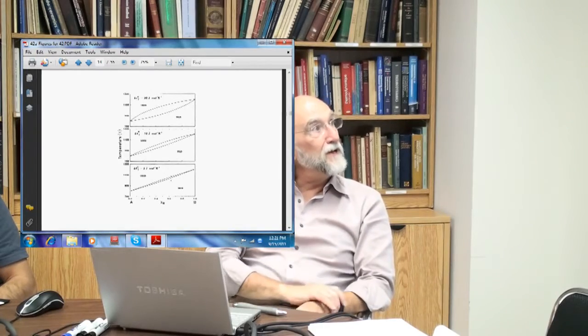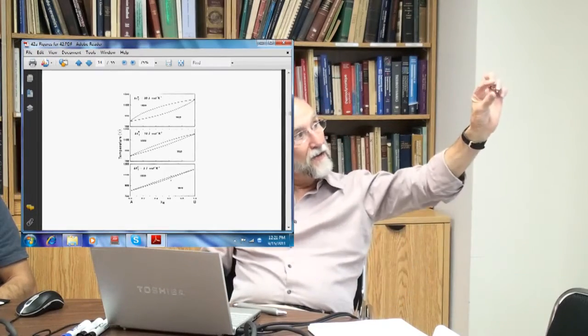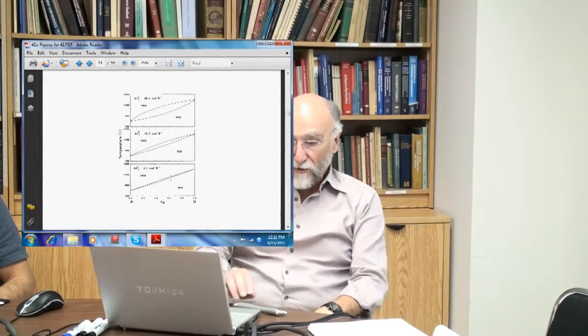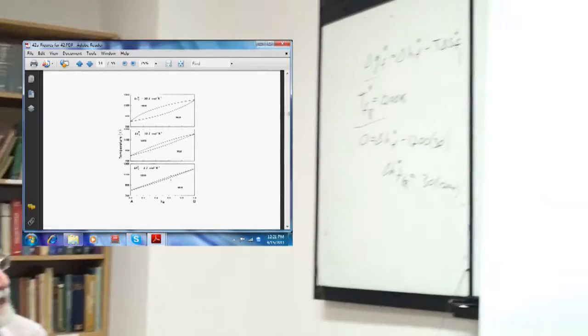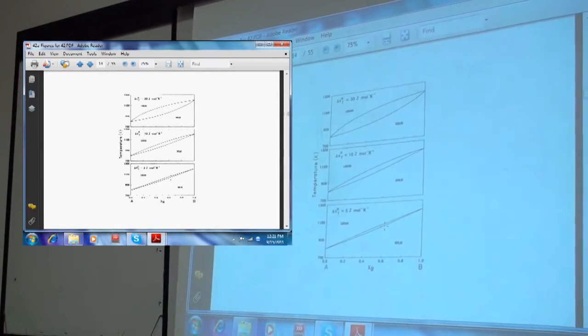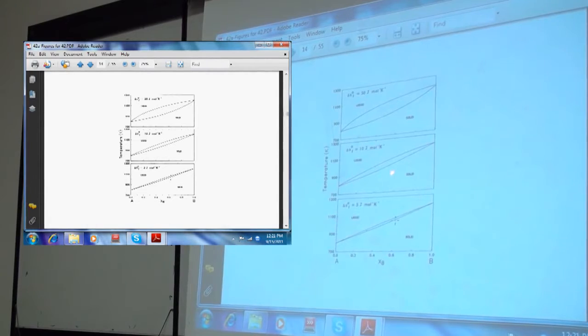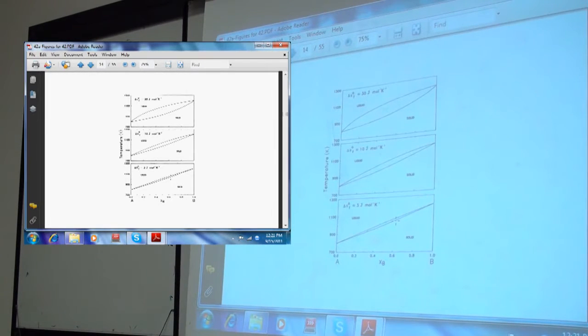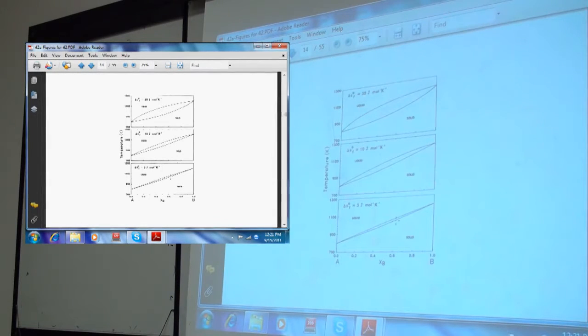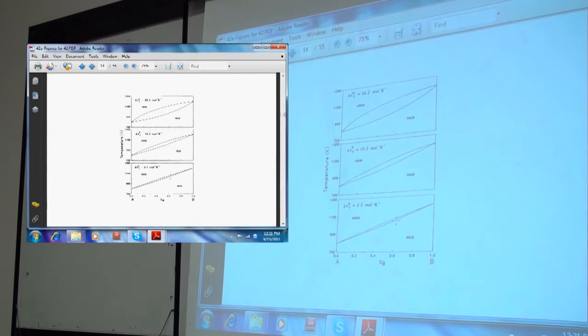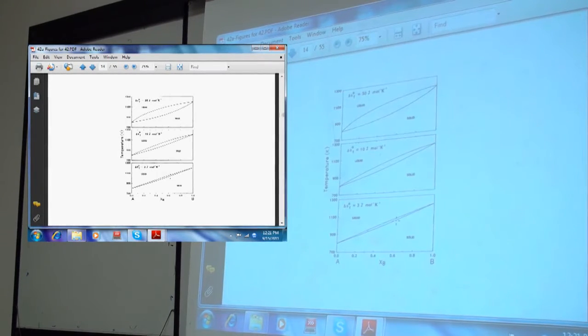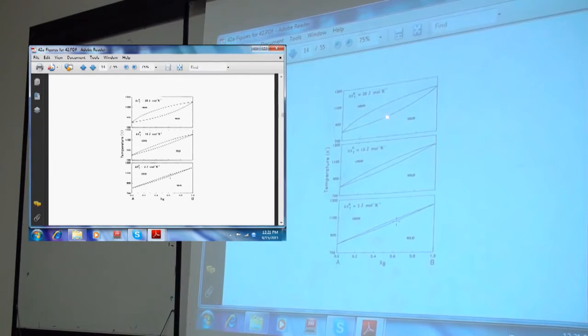So this is rather interesting. What it means is, as the entropy of fusion becomes smaller, the lens becomes narrower. A 10 joules per mole is a typical entropy of fusion of a metal, and so this is a standard width that you might expect for a two-phase region between a solid and liquid metal. Now if you take something like a salt, like sodium chloride, its entropy of fusion per mole is generally twice as much as a metal, mainly because you've got sodium and chlorine, so you really have 2 moles of atoms. You get a bigger entropy, and that's why when you look at salts, you tend to have fatter looking two-phase regions.